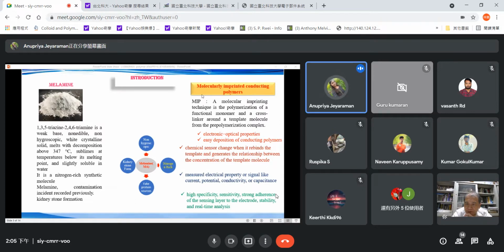Here, melamine detection is done using a molecularly imprinted conducting polymer. First of all, the molecular imprinted polymer technique is polymerization with a functional monomer. Here, the monomer was polyacrylic acid and the cross-linker around the template molecule forms the polymer through the polymerization process. This molecularly imprinted conducting polymer was formed from MIP with the electro-optical properties of polyaniline, with easy deposition and conducting polymer. Here, the chemical sensor signal changes when it rebinds the template and generates a relationship with the concentration of the template molecule. Polyaniline exhibits high electrical conductivity, current potential and capacitance, and very specific selectivity.